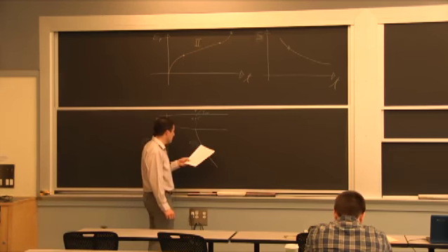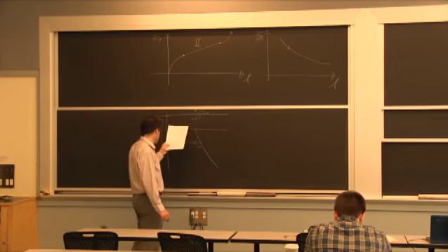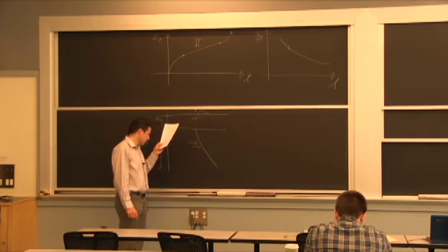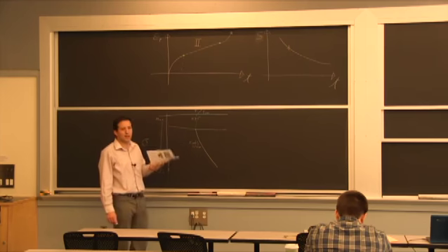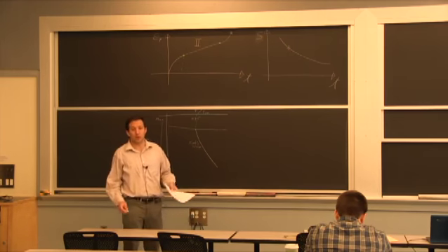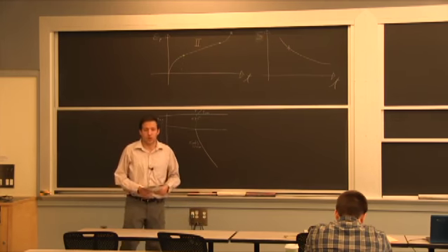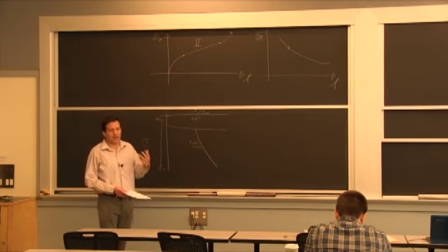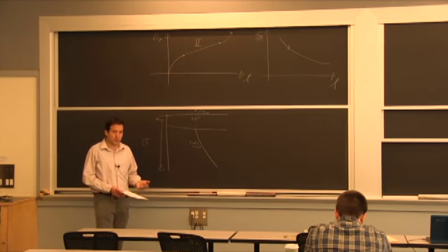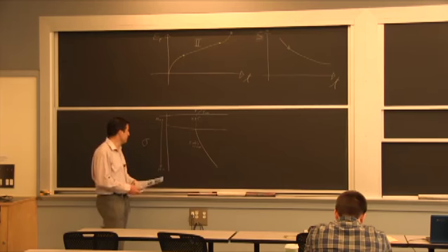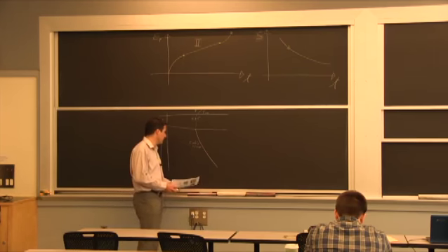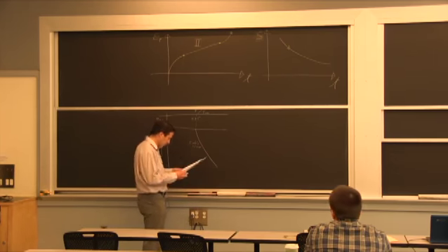It gives us some indication that below that temperature, your strain rate would be less than 10 to the minus 10 per second. Very, very slow. So that's where we were talking. Typically, we consider half the melting point as where creep starts. This chart starts at 0.35, but it's a very, very low rate.